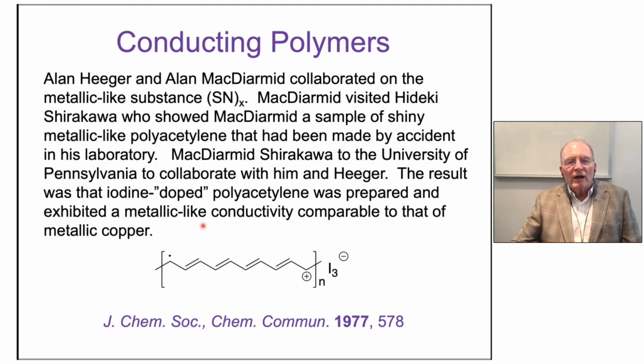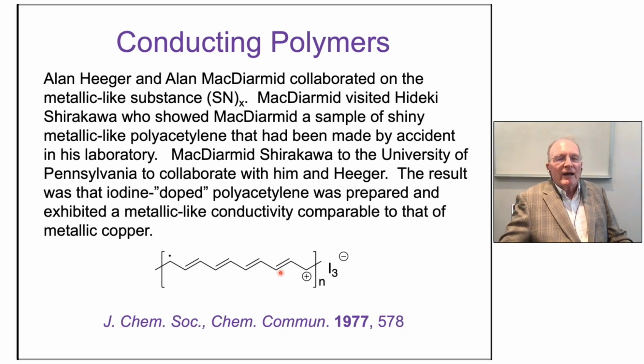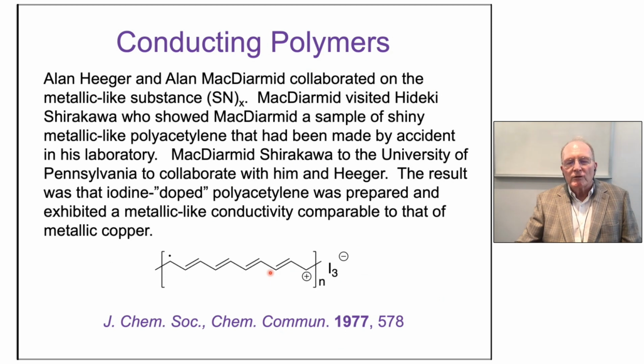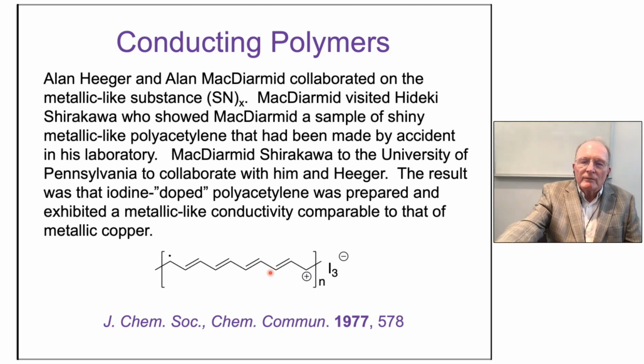And they went on and used stretched polyacetylene and got intrinsic conductivities up near metallic copper. And it's because you have a radical cation, if you like, over about 15 repeat units, which is able, through charge mobility along the chain and through pi-pi interactions between the chains, to become a conductor from being an insulator.